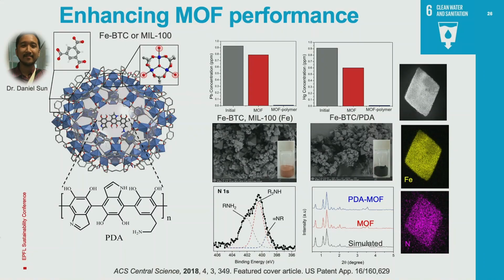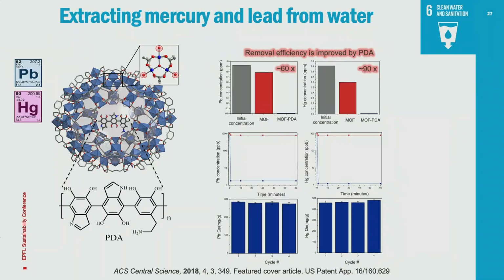So let's look at the performance. Here you see the initial concentration of lead in a solution and mercury, okay? We treat that material just with our MOF. You see it drops a little. It's not fantastic. But when we treat it with the MOF polymer composite, we get below drinkable levels in a matter of seconds, just like what we saw in the work from Cornell, okay? So here you can look, the MOF reaches an equilibrium very fast, okay? But the extraction efficiency is terrible. When we modify it with the polymer, again, like I said, we're at drinkable levels in a matter of seconds. Here is plotted as a function of time on the x-axis. We can also regenerate the materials by various chemical treatment processes.